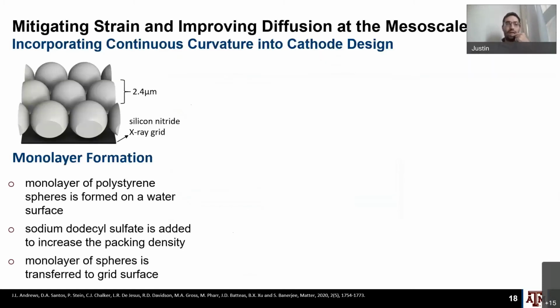And so this has inspired us to ask: can we use curvature, or the way these materials are strained, to change the diffusion and the way these materials lithiate and the different patterns that form, in order to mitigate the strain that evolves from core-shell lithiation patterns?